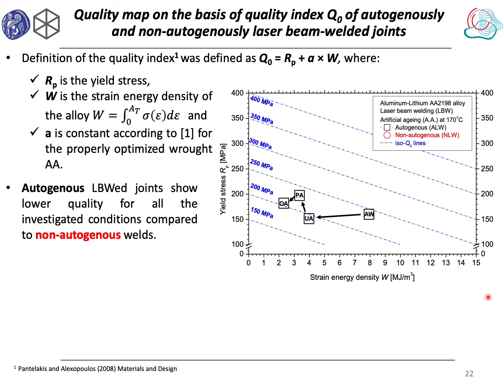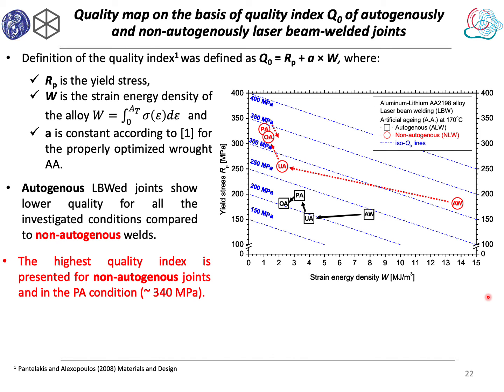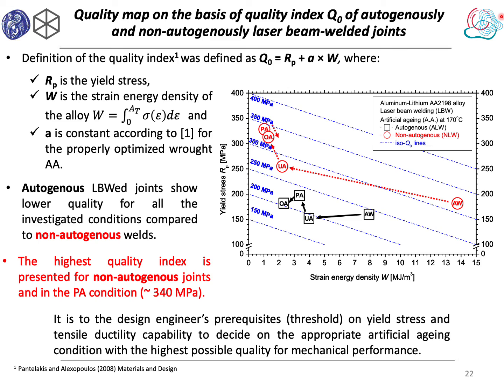The autogenous joints show high quality for peak aging condition and 48 hours. For non-autogenous joints, it can be noticed that the quality index is higher for all the investigated conditions compared to the autogenous. The highest quality index is presented in the peak aging condition, approximately at 340 megapascal. However, it is questionable if the design engineer will use such a material with limited ductility capability, let's say less than 1%. To this end, this diagram may be used to select a specific condition for aluminum alloy 2198 welded joints, which is expected to lead to an acceptable combination of yield stress and tensile ductility.